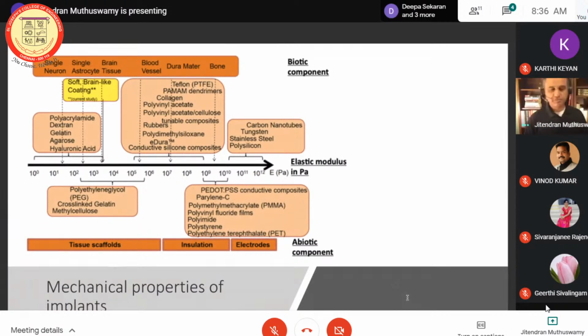The other idea here is regarding mechanical properties of the implants. This is a fairly complex slide. I just want to quickly go over it: this is your biology, this is your material. All these things are the materials side of things. What you have here is elastic modulus, going from the brain, which is here at a few kilopascals, depending on which paper you read and which lab reports this data. It can be anywhere between 500 pascals to 3 to 5 kilopascals. But the materials we put in are on the order of hundreds of gigapascals. That's your elastic modulus. So for instance, silicon is 100 to 180 gigapascals. Most metals are in that range.